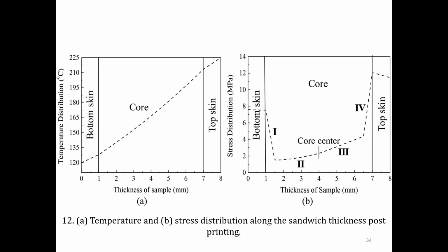So ultimately, why did we take FE simulation help? These FE simulations help in visualizing the stresses at the critical locations, and such locations are presently at the skin core interface, where the stress level changes drastically. Though the simulation did not show any warpage, as expected because we removed that warpage, right?